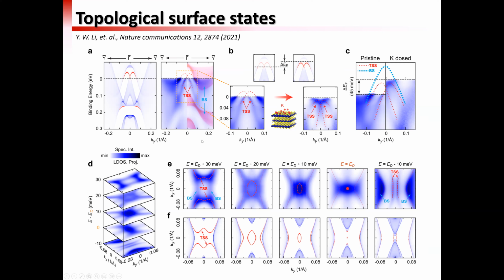Now, this gives us confidence that this material is topologically non-trivial. And in addition to this evidence from the dispersion, we can also see from the constant energy contour, in addition to the bulk state Fermi surface pockets, right? You can see clearly there are additional features that are definitely not the bulk state. This agrees well with the calculation of the topological surface state Fermi surface. So this also confirms that the topological surface state exists in this material.